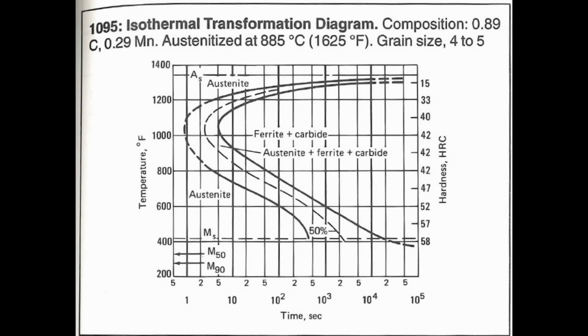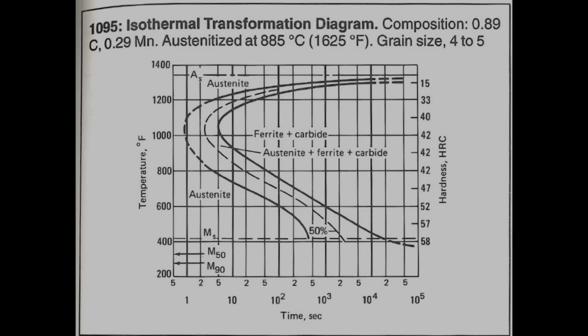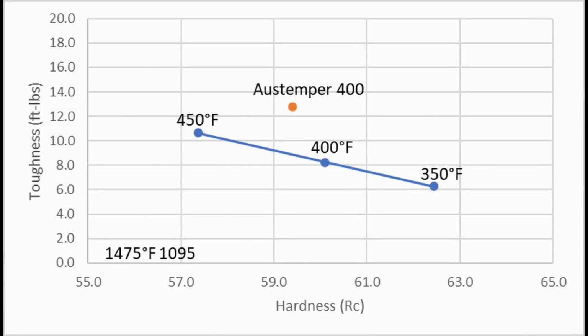Moving on to the 1095, this TTT diagram looks roughly similar to the O1, a little bit less in hardness, closer to the 52100, but the martensite start is close to 400 degrees. Now, when I did an austemper at 400 for the 1095, that gave me just over 59 Rockwell, a little higher than the TTT diagram claimed, and the toughness was not as much of an improvement over the quench and temper 1095 as I would have expected. Though I think there is some other limiting factor for the toughness in this 1095.